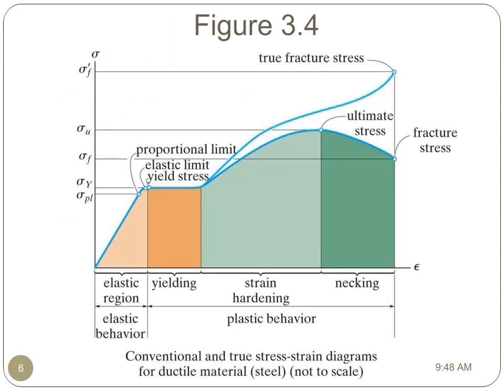This diagram illustrates the different regions of the stress-strain diagram for a ductile material, such as steel. The first region is called the elastic region, and is the range where the stress and strain are linearly related. The point at which the relationship between stress and strain is no longer linear is called the proportional limit. This is followed by the elastic limit, which is the point at which the material will begin to plastically deform, and the yield stress, which is the stress at which the material will yield at a constant rate at a given stress. After the material starts to harden relative to yielding, we see a region called strain hardening, where the strength of the material increases until it finally reaches the ultimate stress, or the highest engineering stress available to the material.